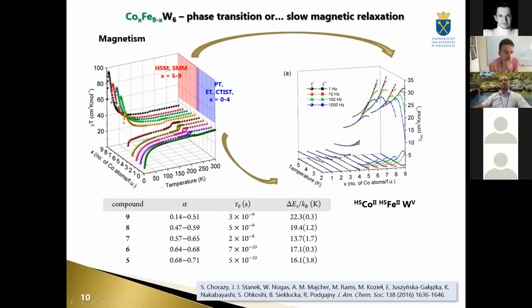So these are magnetic spectra, magnetic moment characteristics for the whole series. Here is the cobalt limit, this is the iron limit. And for cobalt-rich complexes, we do not see the phase transitions. That means that we have a stable composition composed of high-spin configurations of cobalt-2, iron-2, and tungsten-5, which gives us high-spin clusters with quite notable magnetic moment and slow magnetic relaxations with parameters drawn here. Okay, these barriers are not that big, and I must say that they are also obtained with some degree of confidence, but they are present.